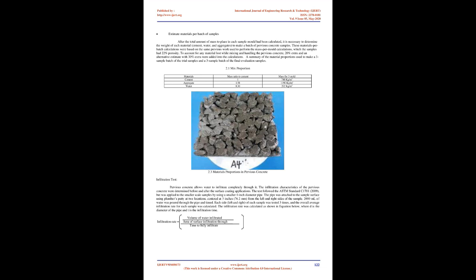A summary of the material proportions used to make a 3-sample batch of the trial samples and a 3-sample batch of the final evaluation samples. The study of pervious concrete mix proportion by the method of 2.3 Materials proportions in pervious concrete. Infiltration test. Pervious concrete allows water to infiltrate completely through it. The infiltration characteristics of the pervious concrete were determined before and after the surface coating applications.